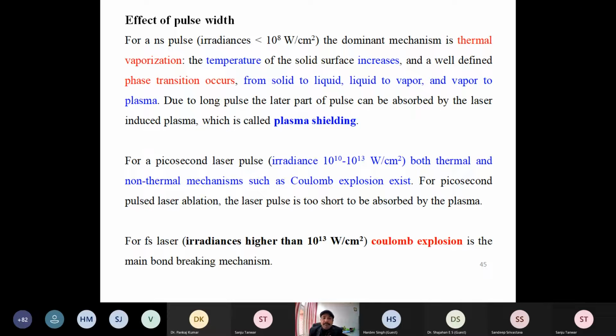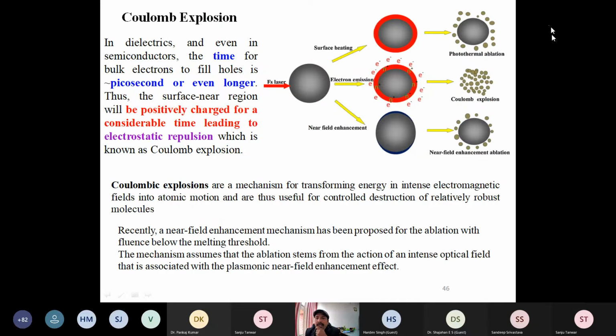In case of femtosecond and picosecond pulses, both types of process take place: the thermal bond breaking mechanism or the non-thermal bond breaking mechanism. In case of femtosecond, the most occurring process is Coulomb explosion. So what happens in Coulomb explosion? When the femtosecond laser falls on the substrate, it immediately removes the surface electrons, and that's why lots of free electrons are available on the surface when the plasma forms. Underneath this layer, positive holes are created, right?